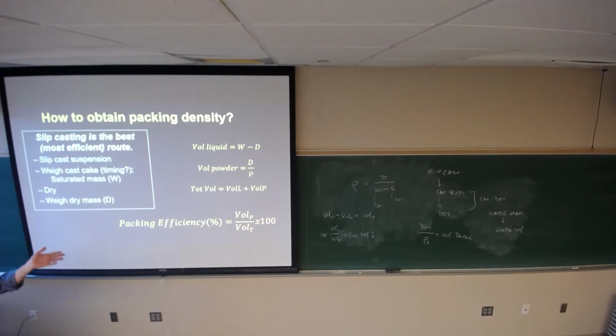I don't need any dimensions. I don't even care if the sample falls apart in the dryer, right? Because it doesn't make any difference. I don't need an intact sample to measure this. I just need to know what the pore water was, which I get by the difference of the saturated minus the dry, and I need to know the skeletal density, which I get from the density of the particle. So this makes it quick and efficient.